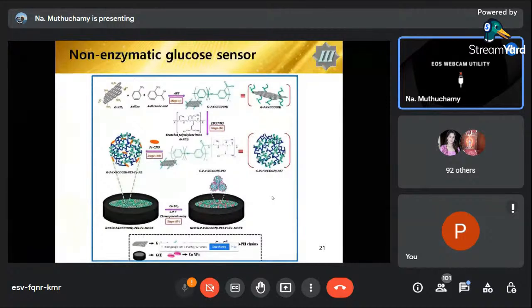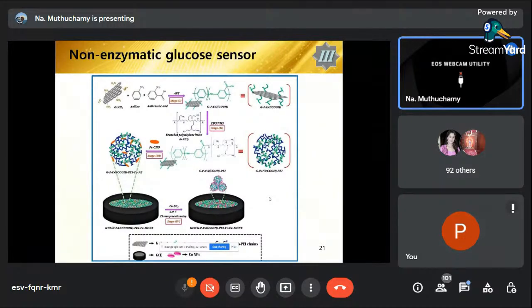The final work is where we fabricated a non-enzymatic glucose sensor based on a multi-component nano bead. These are the multi-component materials which we prepared from graphene polymerized with aniline and anthranilic acid. This is the first stage. Then we functionalized with branched copper nanoparticles to enhance the conductivity. This is the main role. This is one of the complex nano beads.